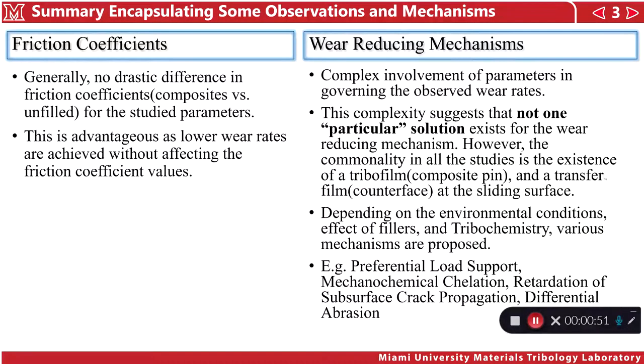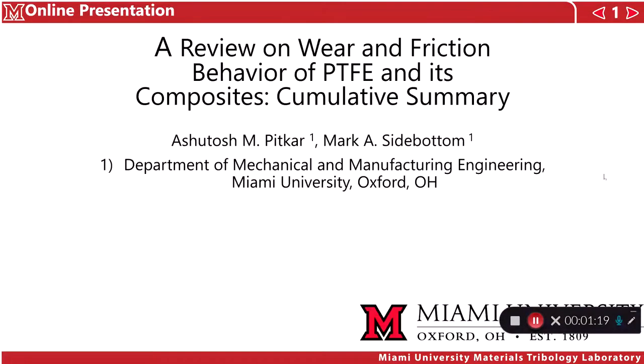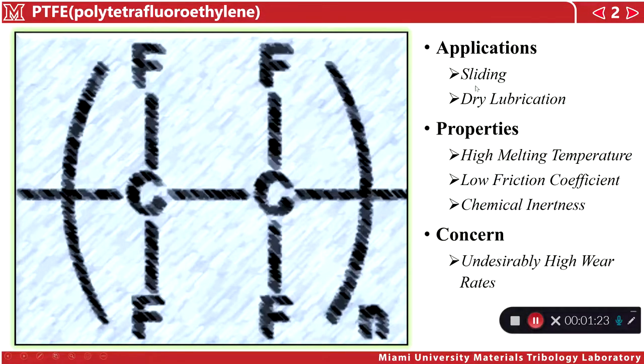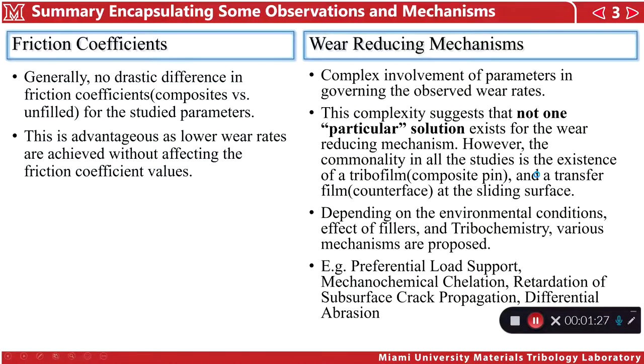After looking at all of the articles, we can see certain similarities between all of them. First of all, looking at the friction values, in almost all the articles we saw that there was no drastic difference in the friction coefficients for either composites or unfilled PTFE. This is a good thing because the reason we use PTFE for sliding and dry lubrication is because of its low friction coefficient. So the fact that we are changing so many parameters and the friction values are not changing by a lot is advantageous — we are improving the wear rate but not affecting the already good properties that PTFE has.